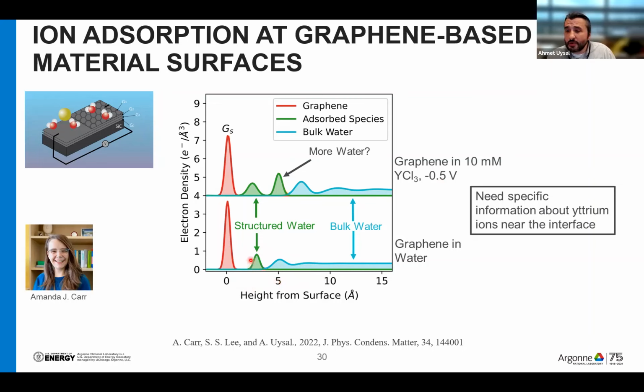Here we represent these with a different color because they appear like a different adsorbed layer, a little bit more persistent than your typical water. This is very well known, you can see structured water on mineral surfaces, also on graphene. This has been observed before. But when we apply potential and introduce yttrium, there are very significant changes to this interfacial water structure. And it is not clear directly how much of it is coming from yttrium. And that's where we need resonant anomalous X-ray reflectivity.